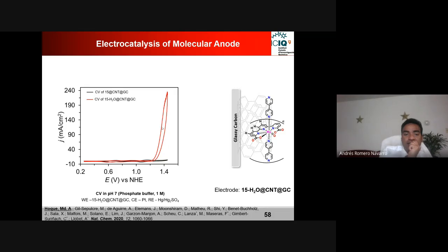And now we are seeing the current density on the scale of almost 240 milliamp per centimeter square. I would say that for our scientific community, this is the first time that with a molecular catalyst you are getting a current density above, let's say, 10 milliamp. So far, before it was a maximum of 10 milliamp, but now we got a huge improvement in this current.